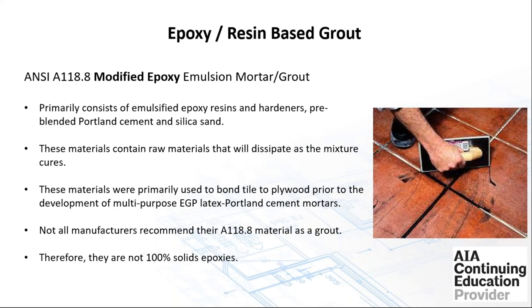118.8, this was primarily used prior to adding latexes to a Portland cement mortar. In other words, you would have a plywood subfloor. I want to bond to that directly with my tile. What am I going to use for an adhesive? We know that cementitious products will not bond to plywood without a latex. So we have to go to an epoxy that would be the adhesive, or that mortar, at that time. Once we started getting the latex added mixtures for the Portland cement mortars, then that kind of went away. It's not as popular these days. And not all manufacturers have a 118 material as a grout. They still have it just as a mortar.